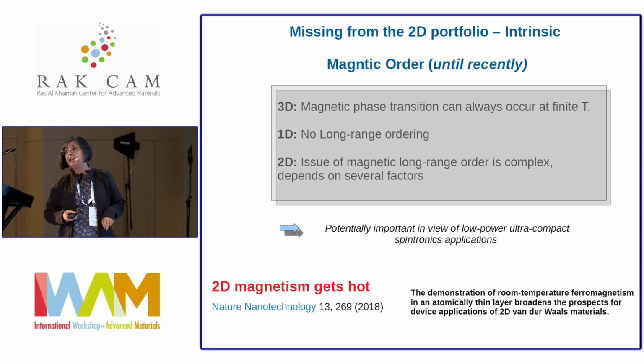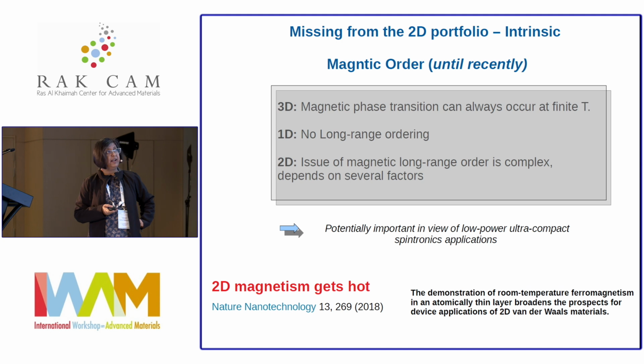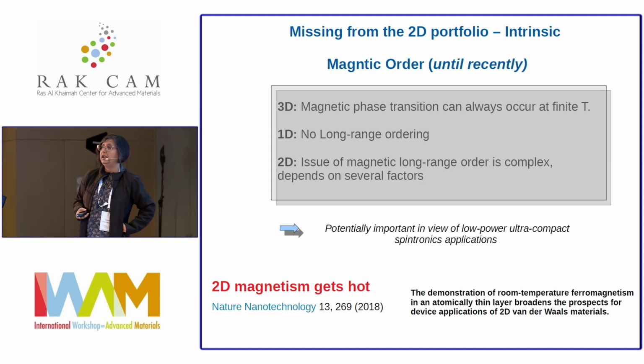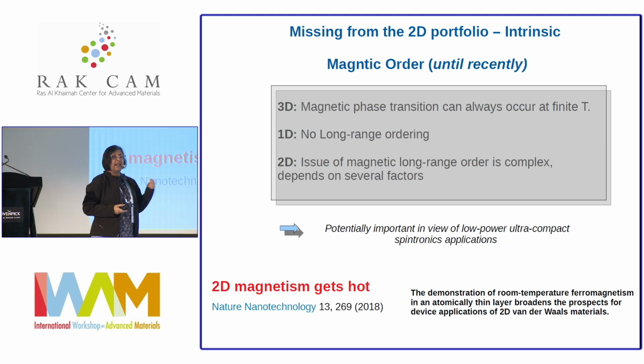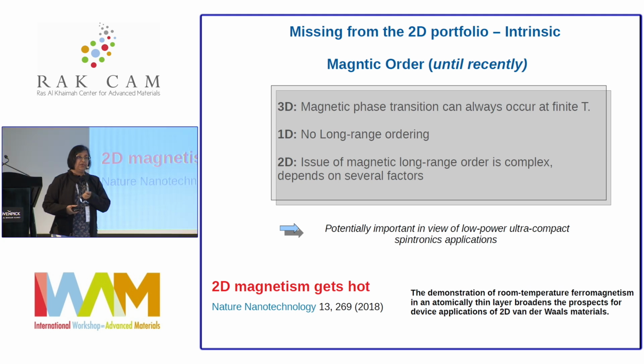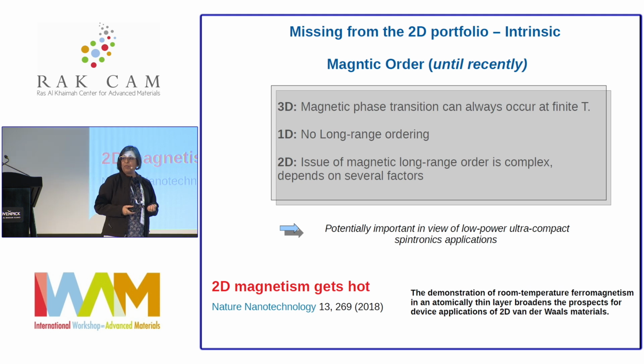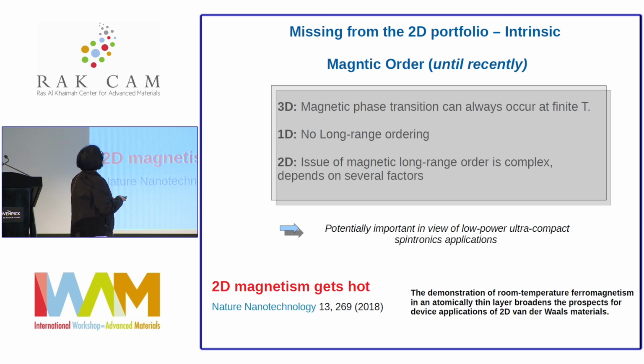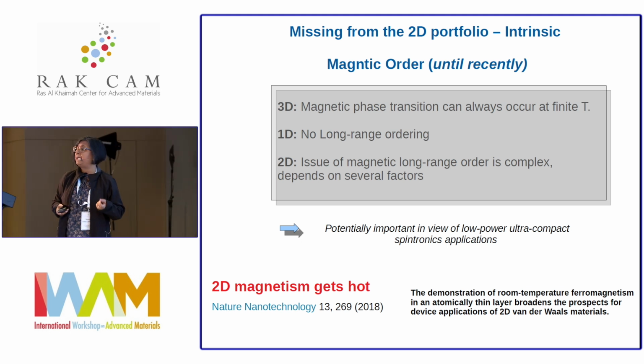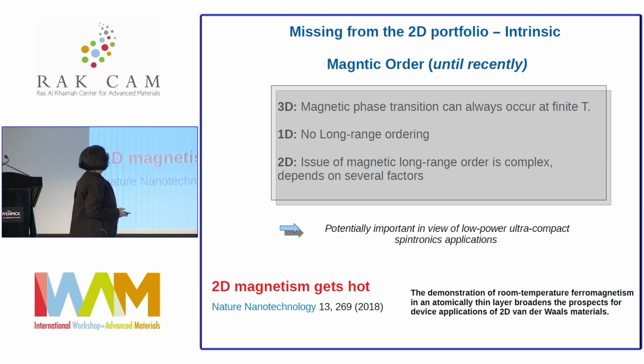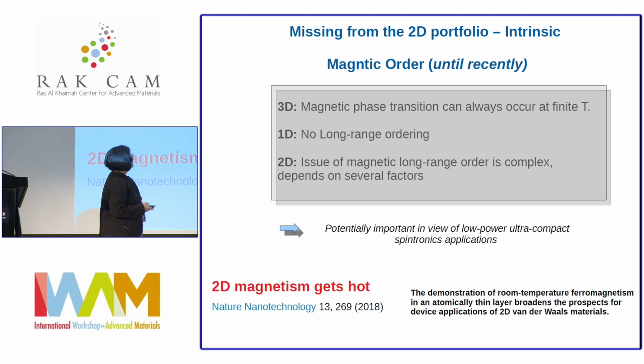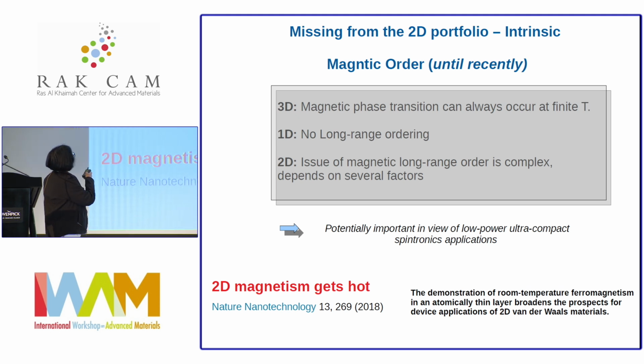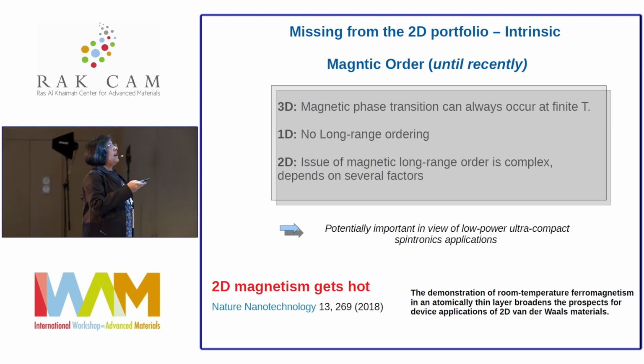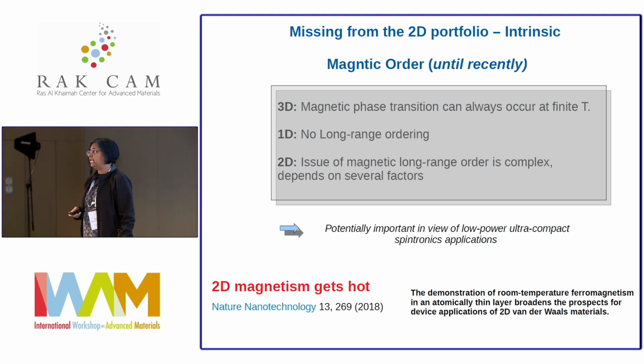But what has been missing in the 2D portfolio until very recent time is the magnetic order. By putting adatoms on graphene by external means, there have been attempts to engineer magnetism, but what we are talking about is the intrinsic magnetic order. So the magnetic order depends on the dimensionality of the system, as you know from your undergrad training, that in 3 dimensions, a magnetic phase transition can always occur at a finite temperature. For 1 dimension, there is no long-range order. In 2 dimensions, the issue of magnetic long-range order is complex.